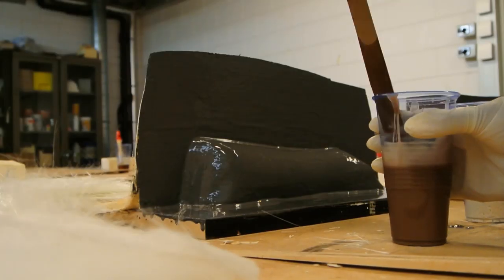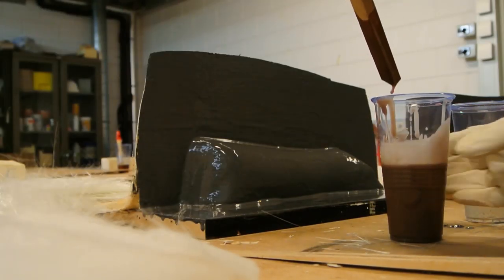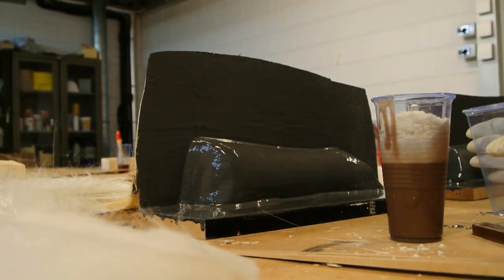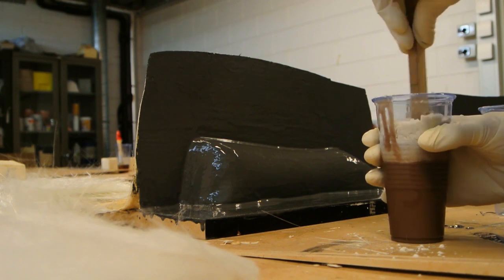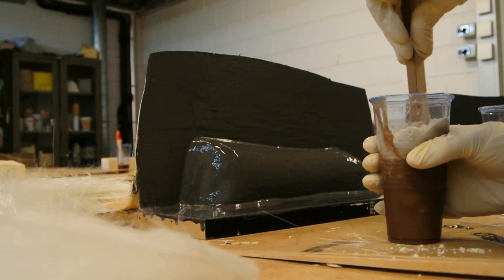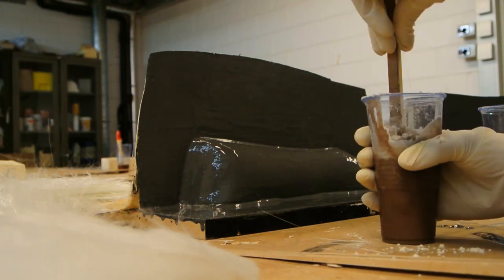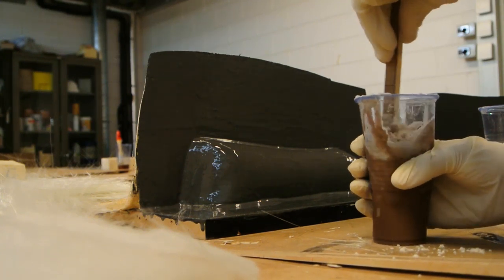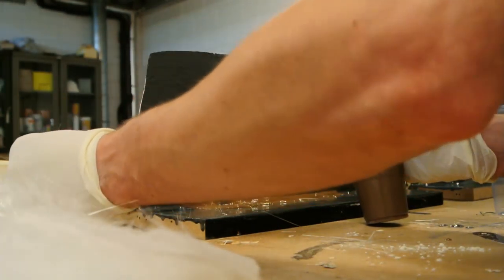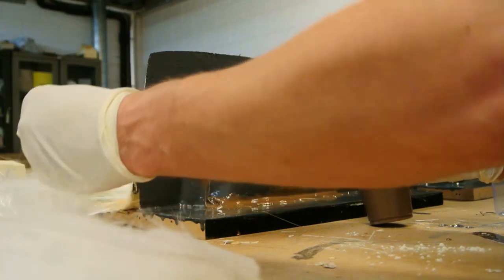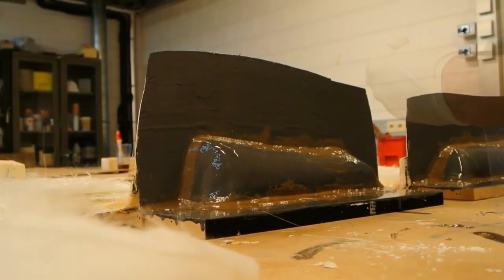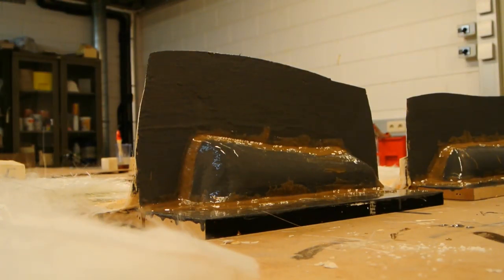Once that's done, I've tried a new technique with tooling resin from Vosschemie with cotton flakes to make a thicker paste, like making Bondo out of polyester resin. It's less fluid and easier to apply. On the undercuts, I add some of this in a caramel-chocolate paste state for a nice filling.